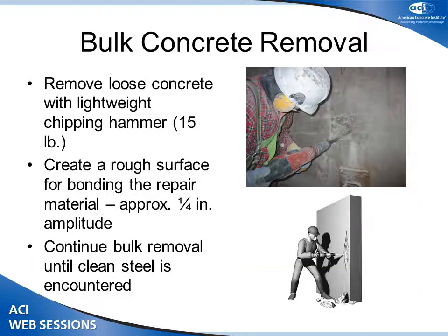So, some of the steps in the process. The first step is bulk concrete removal. So basically you're going to remove the loose concrete with a lightweight chipping hammer. Usually you'll refrain from using heavier hammers or jackhammers because we want to prepare the surface and remove the deteriorated concrete, but we really don't want to create any additional damage to the base structure by cracking or damaging it. So lighter weight hammers are typically involved. And plus, these are vertical and overhead in orientation anyway, so the lighter hammers are easier to handle. You want to have a rough surface for bonding the material. So it says here approximately 1/4 inch in amplitude for the surface. So you get, in addition to some type of chemical bond between the repair material and the surface, you also get a mechanical bond with the roughened surface.